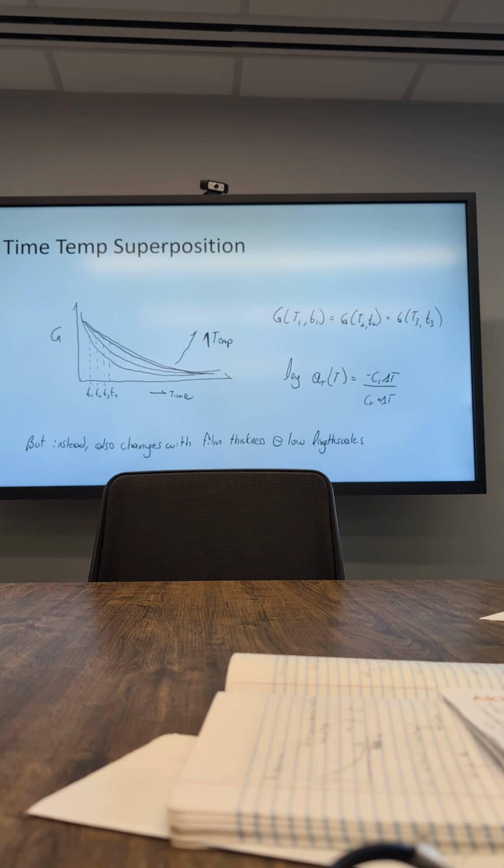But the thing is, this is where I have trouble relating it, because from what I can think, this paper is saying that the WLF and the time-temperature superposition don't really work in really small scale cases, or they may, but there's also a new feature, that this can change with the thickness, right? Yeah. Because now we have another thing that's affecting these parameters, not just temperature, now we have film thickness, it doesn't completely follow the time-temperature superposition, and the WLF equation falls apart. And I think that's what they meant. What do you think, Jude? Yeah, that's what they say.